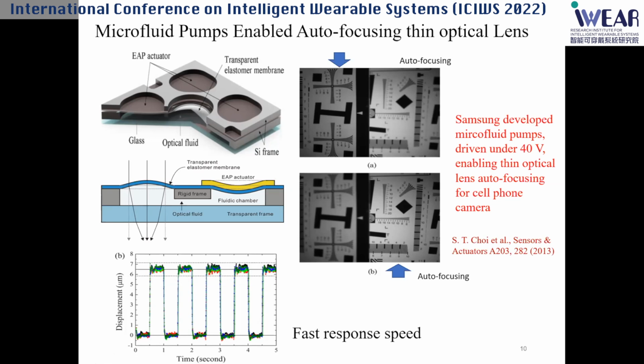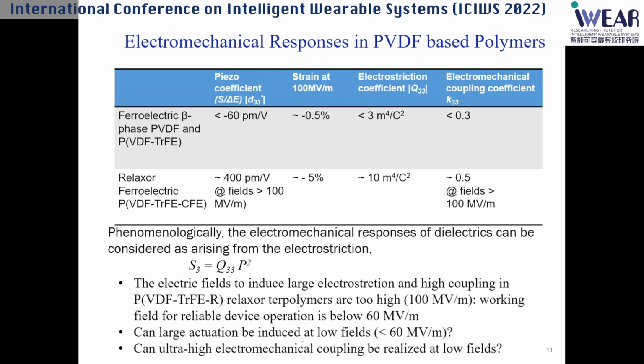But also through those device works, we get a lot of feedback, and a lot of people ask us, well, although this terpolymer is better than the PVDF TrFE copolymer - for example, PVDF TrFE copolymer's piezoelectric coefficient is about 60, now we can get 400, but it needs a high electric field, 100 megavolts per meter. Also, we increase the strain about 10 times, but again it also needs high voltage, and the electromechanical coupling also occurs at high voltage, right?